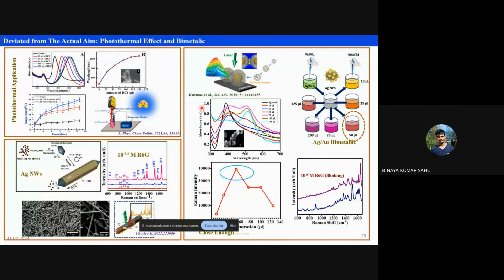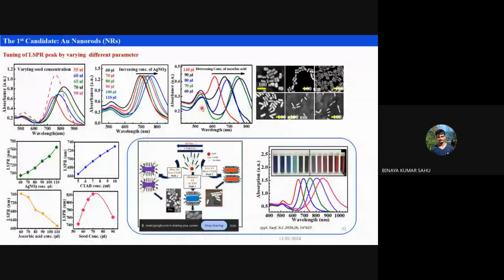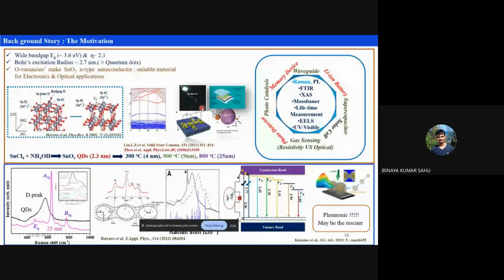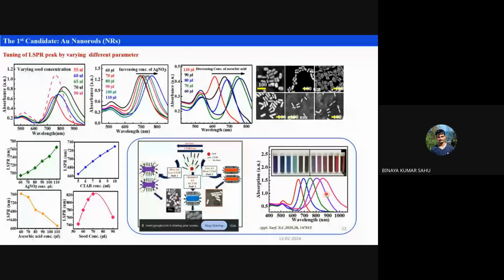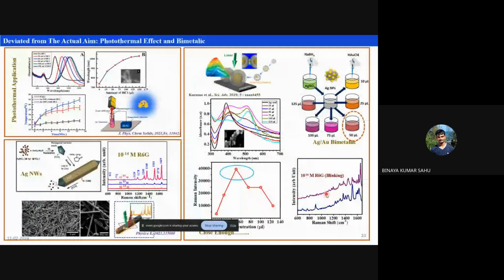Because in the paper that I followed in the very beginning, for tin oxide they could go up to 10 to the minus 16 molar of R6G. So I understood that these gold nanorods are not going to help. So I changed my material. We again prepared some silver nanowires, and that went to 10 to the minus 14, close enough. But still that was not possible.